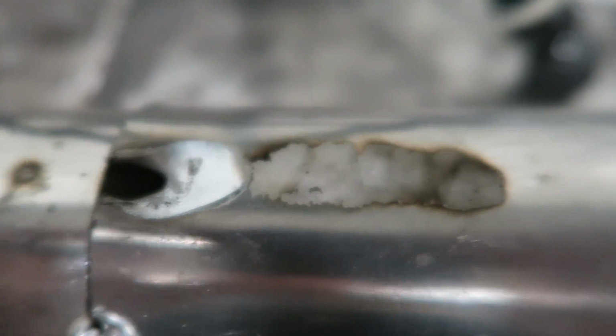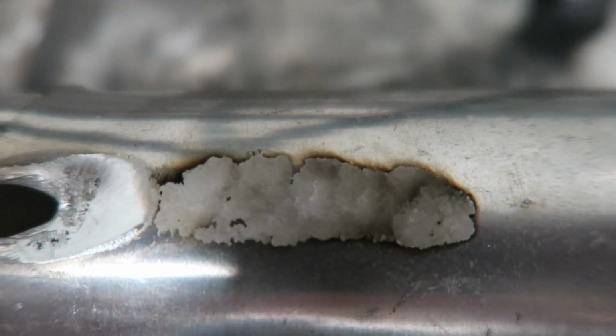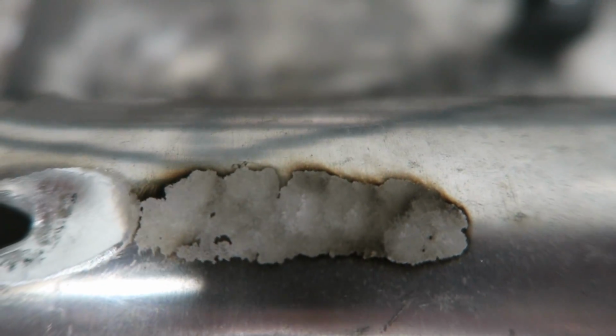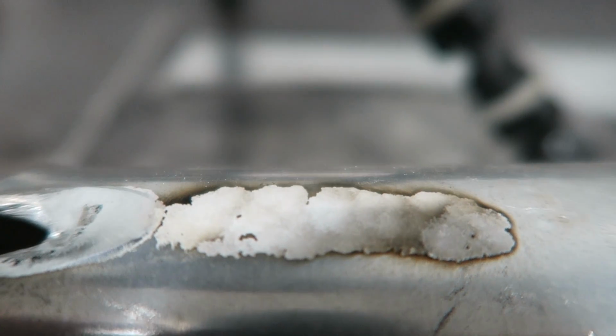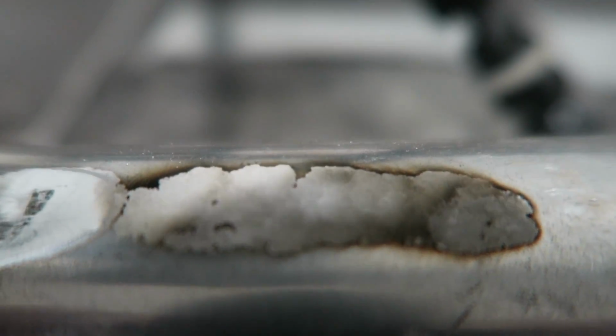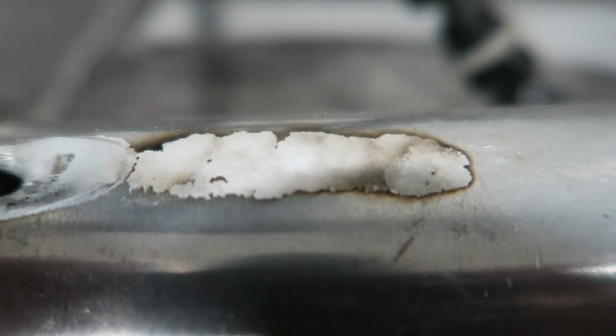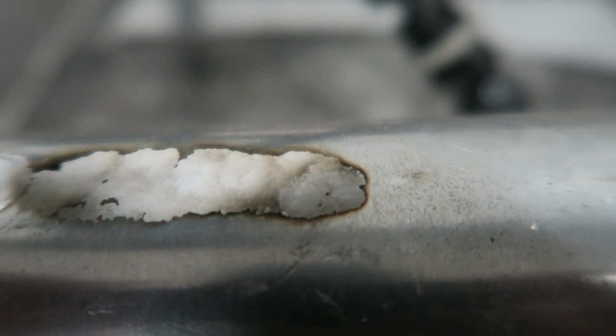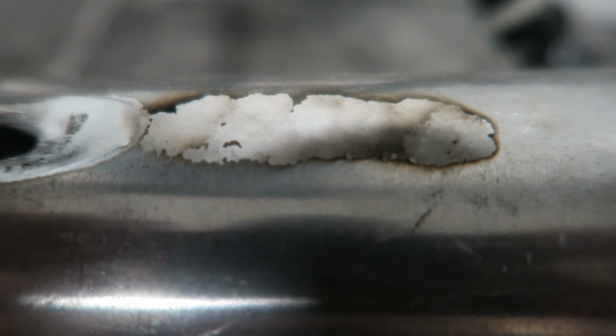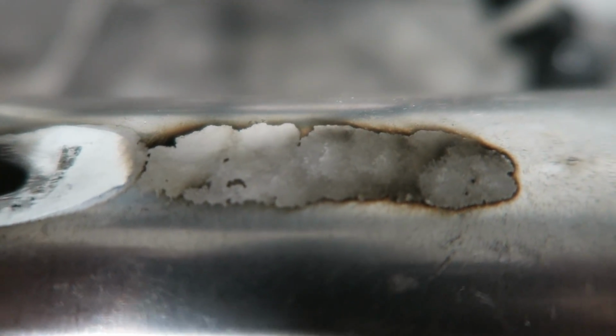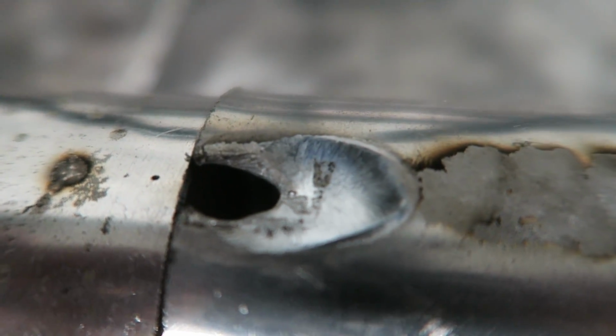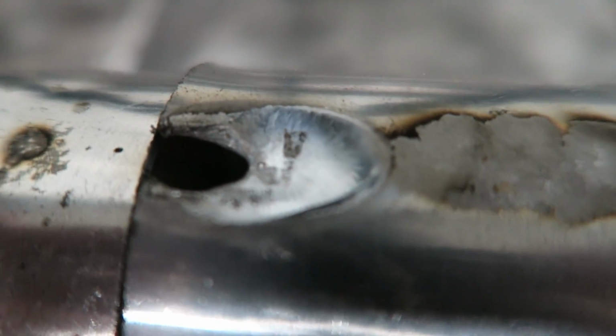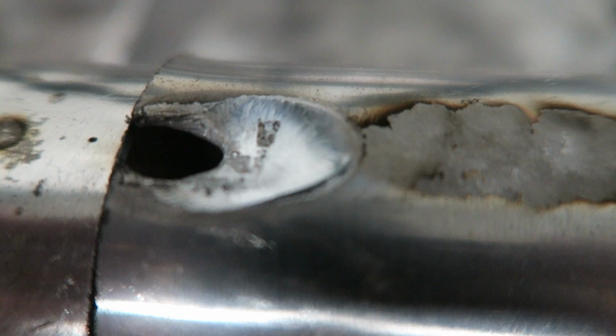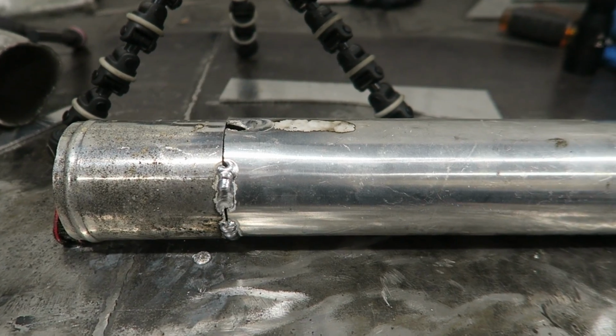Now the second thing I was talking about, the cleaning action, that is me using low amperage, and you can see the color, that whiteness that happens is actually the burned up remnants of the oxidation layer that was on the aluminum. That is what you have to burn through first in order to actually get a clean puddle that looks like that. And over the next 10 minutes or so, that puddle will actually oxidize once this metal cools down. Now, just to show you guys something interesting, if this thing will focus, there we go, there you go,